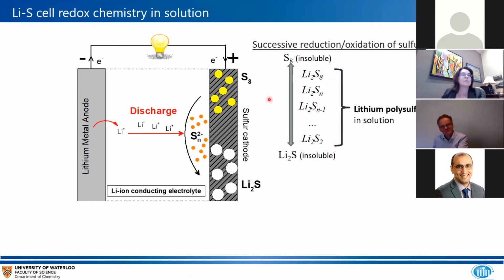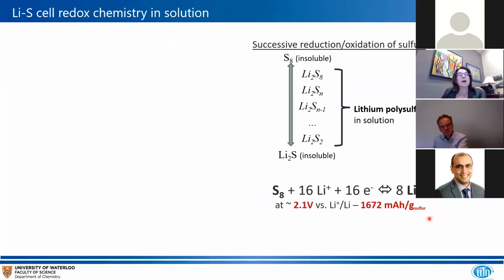And it really is a problem because the dissolved polysulfides drift back onto the lithium metal anode, whereupon they become chemically reduced and ultimately passivate the negative electrode. And they also result in self-discharge, which reduces the Coulombic efficiency. So while this has a really tremendous theoretical capacity, both gravimetric and volumetric, the practical capacities barely reach 1,000 milliamp hours per gram, which is kind of a metric. It's basically coulombs stored per gram.